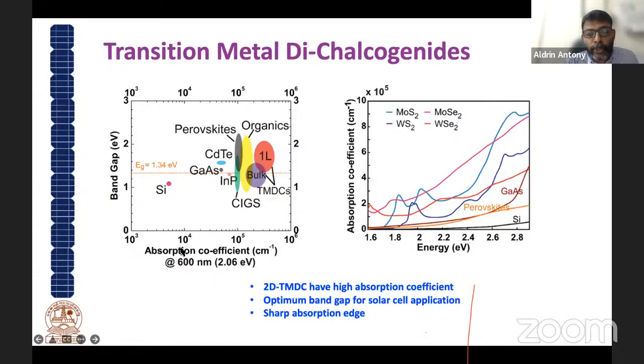And if you look into the absorption coefficient here, you could see it's huge. Normally, silicon is a very low absorption material. Gallium arsenide is nearly 10 to the power of 5. And you could see this absorption coefficient is very high, of the order of more than 10 to the power of 5, for 2D materials. And if you compare the different absorption curves, this is a gallium arsenide curve.